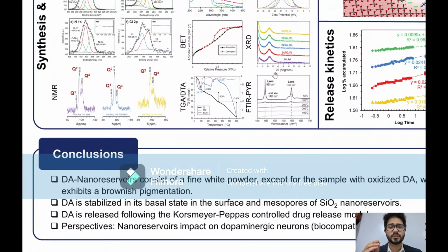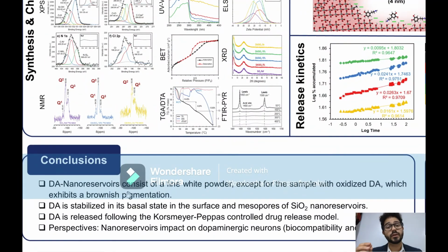With all of the above, research so far has shown that nanoreservoirs consist of a fine white powder when dopamine is stabilized in its basal state and a brown powder when it is oxidized. Dopamine is stabilized on the surface and mesopores of silicon dioxide due to the acid sites and their negative charges, and finally, dopamine is released in a controlled manner following the Korsmeyer-Peppas model.